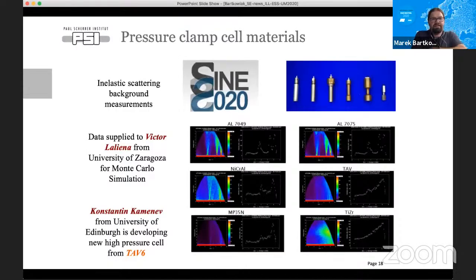Seen in 2020, another example for optimization is the look for new pressure cell materials for inelastic scattering. There, together with theoretical support from the University of Zaragoza, we did some studies on several materials, and it is apparent that TiZr, which is a titanium alloy, seems to be a very good candidate to make inelastic cells. You can see in the spectra, the one in the middle on the right, that's TiZr, that there's basically a homogeneous background, more or less. So you can expect that in the upcoming years there might be a new generation of pressure cells for inelastic scattering.